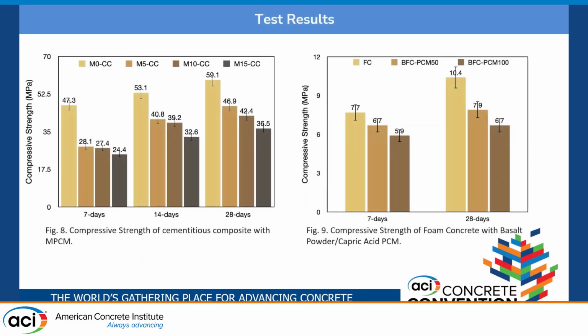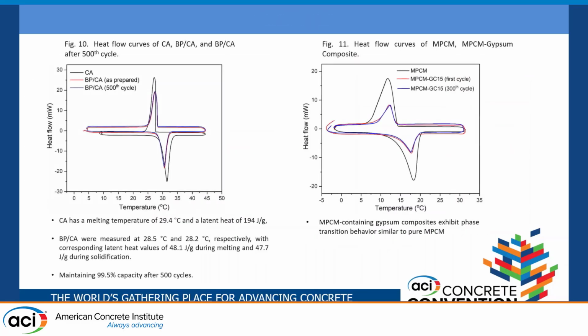So as I said, unfortunately, the mechanical performance has been affected by incorporation of the phase change materials. Even 15% of the PCM decreased the 28-day compressive strength by around 30 to 40%. But we definitely can optimize this by taking advantage of thermal properties. Again, although we have tried basalt powder and capric acid shape-stable PCM, it also affected the mechanical performance. But there are some interesting results here.